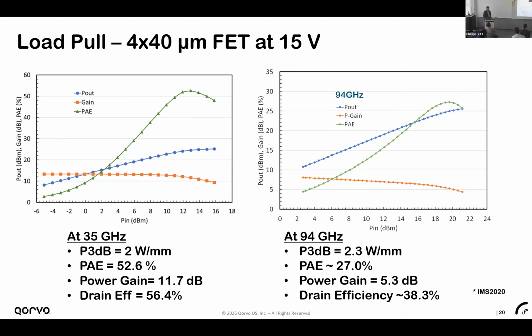And basically I'm showing the same device measured at different frequency ranges. At 35 gigahertz, the PAE is high, but when you go to 94 gigahertz, as I mentioned, the efficiency decreased to 27%. But typically we don't expect the maximum output power to change a lot. So at lower frequency or high frequency, the total output power should stay about the same.